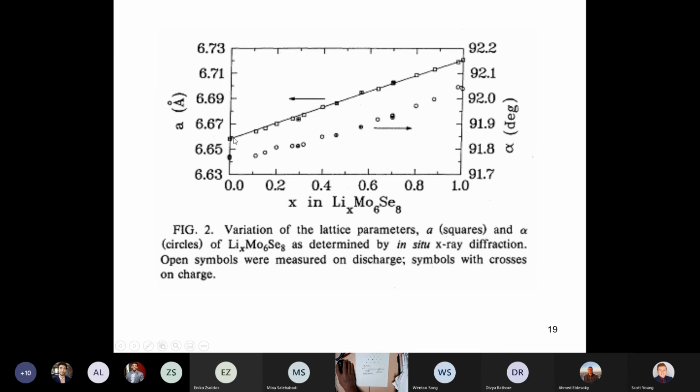So the Coulomb interaction is incredibly small. So it's just a fluke, really, that you end up in a situation where you have a very long range interaction, which can be well treated by mean field theory, and no appreciable near neighbor repulsive interactions due to Coulomb.